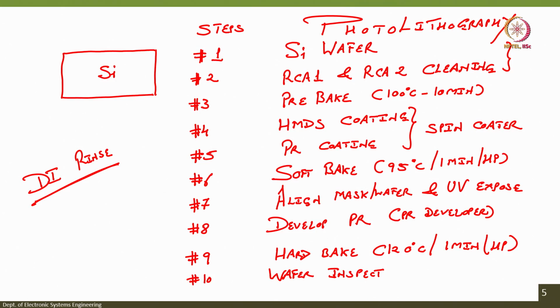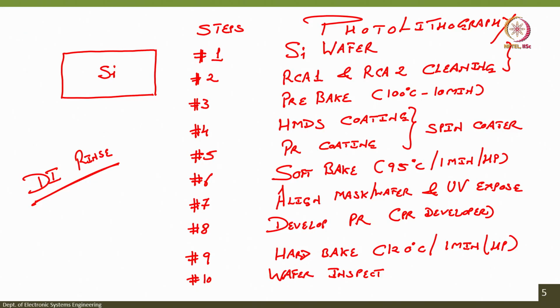The next step is you take the mask and align it with the wafer, and expose it under ultraviolet light. The exposure time and the dose depend on the material that we are exposing. Next step is to develop the photoresist using the photoresist developer. Next step is the hard bake, at 120 degrees centigrade for 1 minute on a hot plate, and finally you need to inspect the wafer. Easy. Now let us take an example so you further understand.